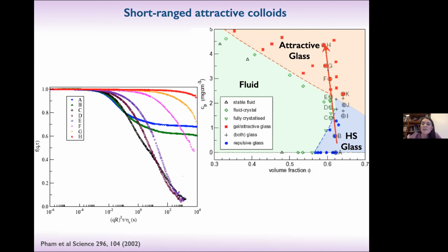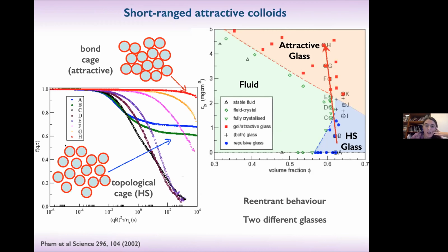You continue to increase the polymer concentration and you now have a second arrest, a different arrest. You see that the shape of this correlator is completely different from this, so it's a completely different glass. And actually, if I was able to enlarge this figure, here you would have a kind of plateau, because what happens is that here the particles are much more localized, and so the two-step takes place at a much higher plateau value of the density correlator. And so this behavior was explained in terms of two different glasses.